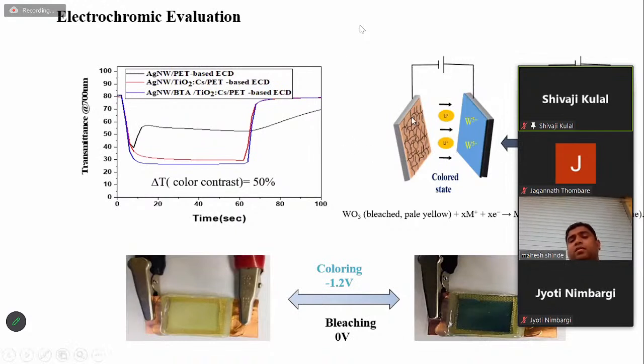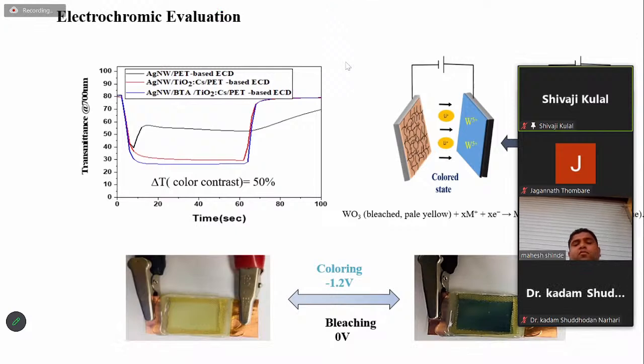So this is the basic principle of the ECD. Why is tungsten used for the electrochromic device? Because when we apply the potential, the tungsten oxide is reduced, which makes it blue. And when there is no voltage, the tungsten oxide becomes yellow again. So you can see this is the window in the normal condition. When we apply the voltage, it becomes blue. Here we get about 80% sunlight, and in this case we get about 50%. We can restrict 50% of the sunlight, so your home is in a cool mode because of the coloration of the window. And many airlines are using blue color windows, so they are using tungsten oxide for their application.